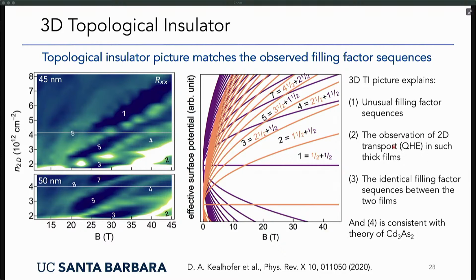And it also explains the 3D TI states, why we get a quantum Hall effect in such thick films, okay, where we wouldn't really expect any quantum confinement effects and subband levels yet. So these films are 45, 50 nanometers thick. We wouldn't expect yet strong confinement effects. And it also explains why we get relatively thickness independent filling factor sequences, because independent of that, 45 and 50 nanometer films will both have the same types of topological surface states.